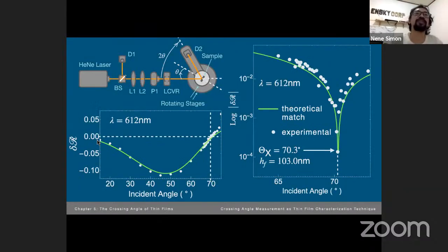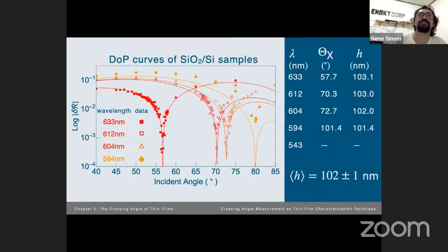So here is an example of the data points we measured using our setup for 612 nanometer wavelength. The white circles here are the measured data, and the matched theoretical curve is the green curve here. So this is the normal scale, and we have here the logarithmic scale. And from the logarithmic scale, based on the data, the position of the crossing angle is 70.3 degrees. And if we match our theoretical curve, we have a measured thickness of 103.0 nanometers.